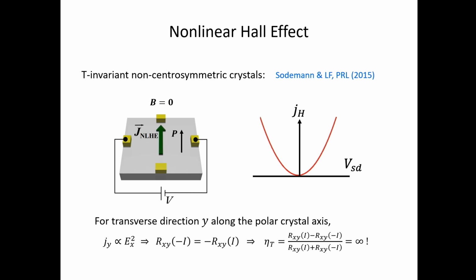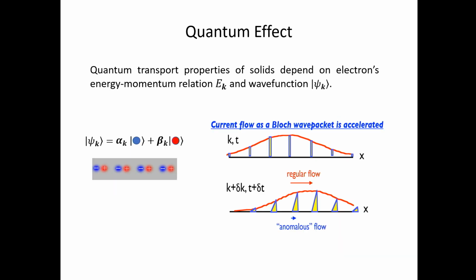And in this case, if we look at how the resistance behaves, the resistance actually changes sign when you flip the applied voltage, and this non-reciprocal coefficient will actually diverge. This is possible because I have 0 Rxy to begin with. That's unlike in the case of the longitudinal effect, where I have to compete with the usual Ohm's law. Here in the transverse direction, to the linear order, because of time reversal symmetry, there's no Hall resistance. But then beyond the linear response, there can be a quadratic effect. So we call this the nonlinear Hall effect.